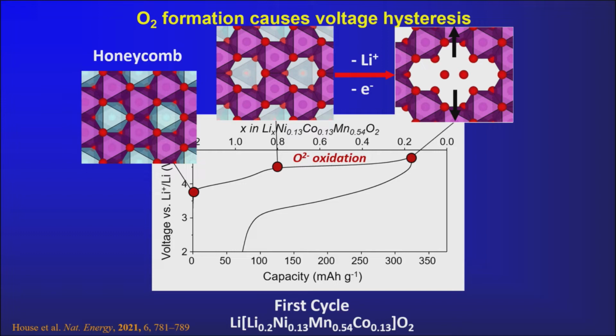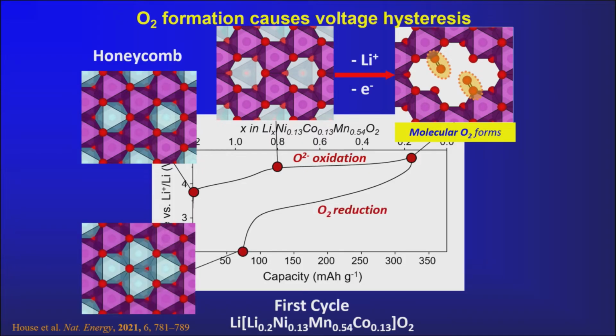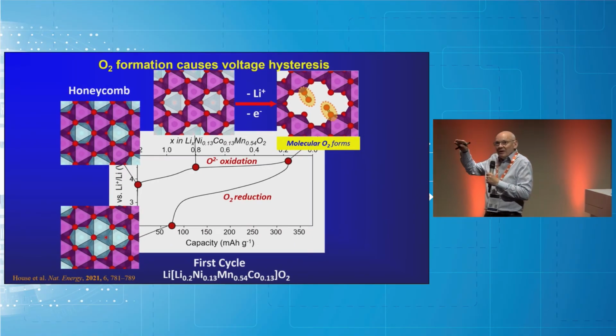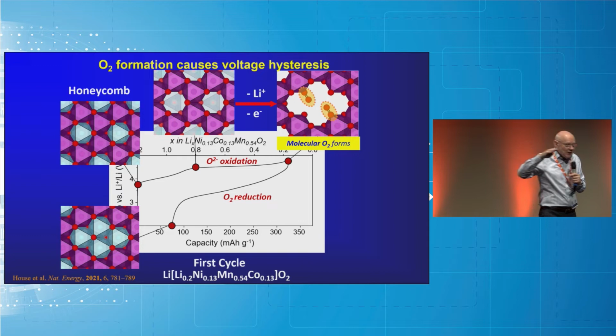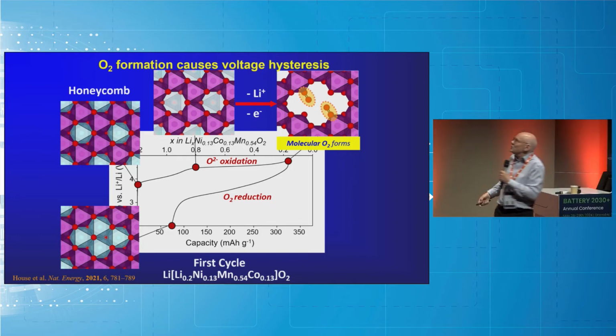Now, these two oxygens are not just going to sit there on their own. They're going to bond covalently to these oxygens to form two O2 molecules trapped in this void. And then when you discharge, when you put the lithium ions back in, they go back into these sites, because the transition metals don't have time to reorganize. If you heat this up to a couple of 100 degrees, you can re-establish the honeycomb structure. But at room temperature, that doesn't happen.